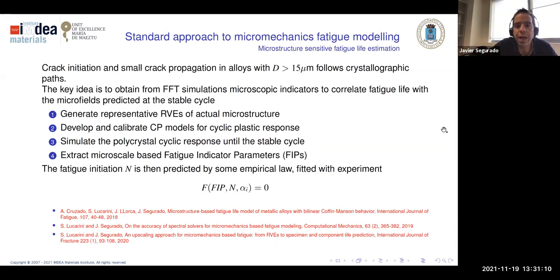Second, we are going to calibrate the crystal plasticity model that takes into account the cyclic response. It is a bit different to the one that I have shown, I will show you now. Third, we're going to simulate the cyclic response, so the full field simulation for several cycles, 3, 4, 10, until we reach the stable hysteresis cycle.